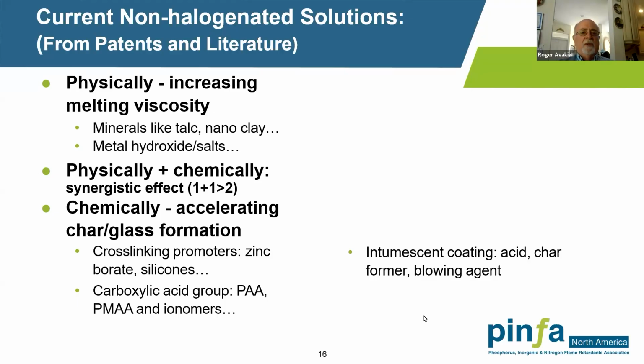There are some other methods as well, which are more chemically accelerating this char or glass formation so that basically you're encapsulating the melt so it doesn't drip. This can be done by various types of materials, typically cross-linking promoters like zinc borate, silicones, and some other materials as well that we'll talk about, as well as some ionomers, for instance, polyacrylic acid salts and polymethyl acrylate ionomers and other ionomers as well. Also, intumescent type materials, with some interesting ramifications of making intumescent materials, even coating inorganic materials, such that we do have an acid source, a char former, and a blowing agent. So there are many different approaches to developing this drip suppressant behavior, and we're going to dive into some of those in a moment.